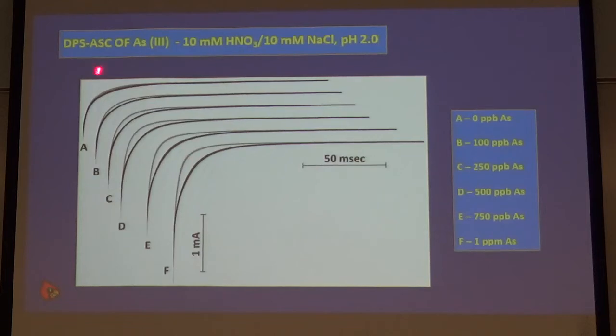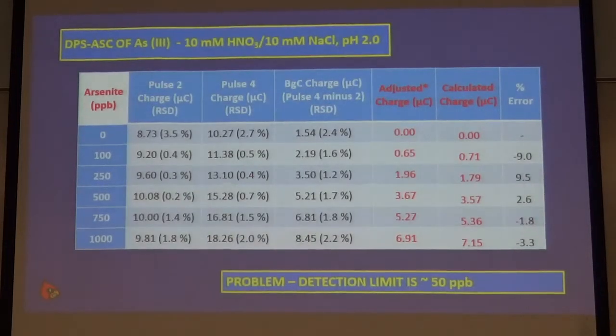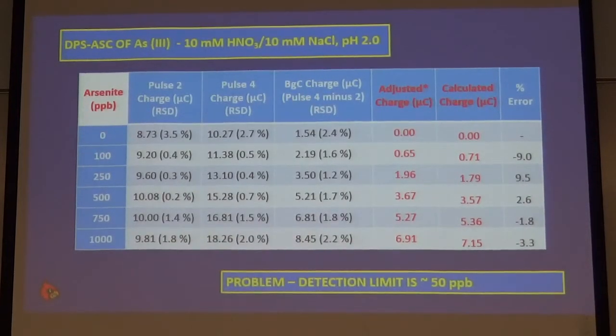When we do that with different concentrations of arsenic, we get these crescents. That A is for the blank, where there's no arsenic present. As we go on out here, we're going from 100 ppb arsenic to about 1 ppm arsenic. You can see the signal, which is the crescent, is increasing as we go out. That's a good thing. If we go to a table and turn that all into numbers, these are the different concentrations.